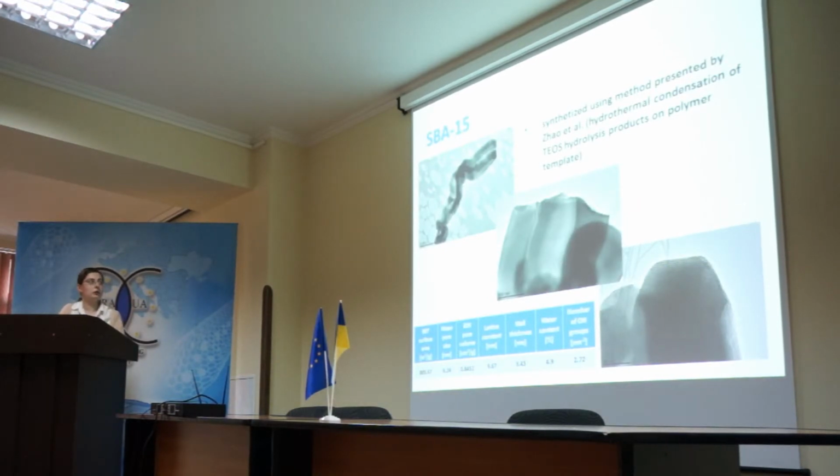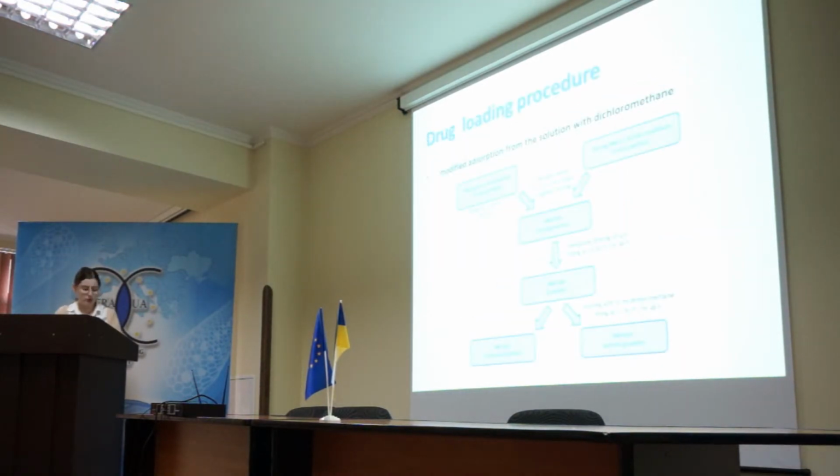In our study, we used as ordered mesoporous silica SBA-15. It was synthesized using the method presented by Zhao and co-workers. It is a typical hydrothermal condensation reaction of TEOS hydrolysis products on a polymer template, as you can see in this TEM picture.